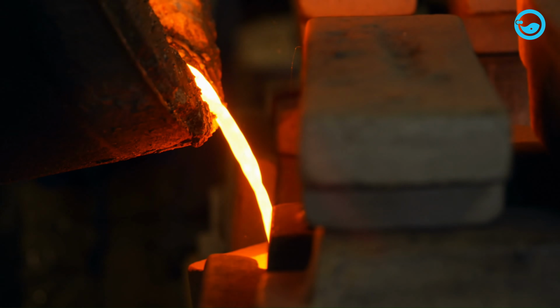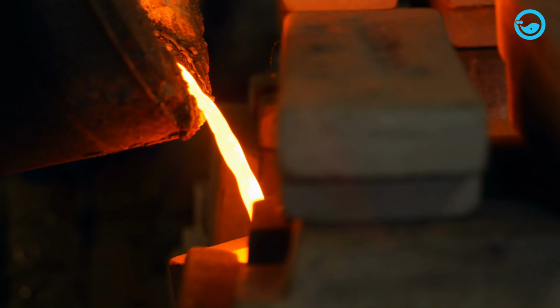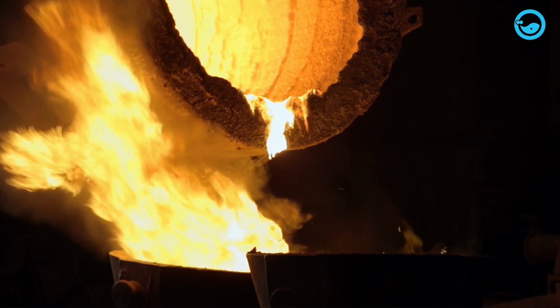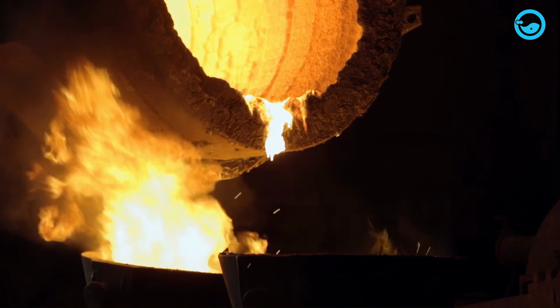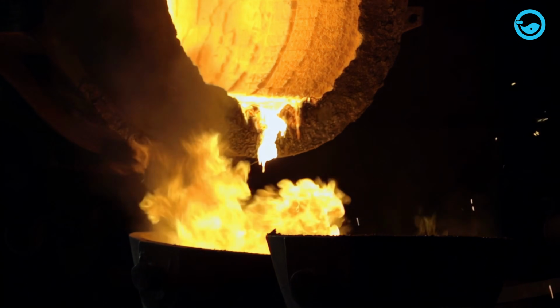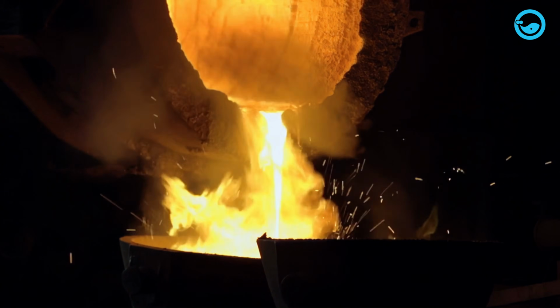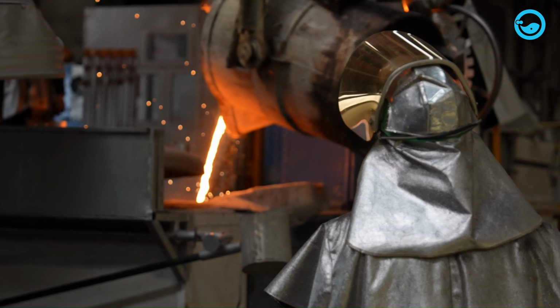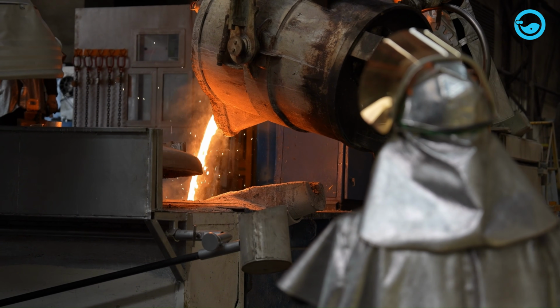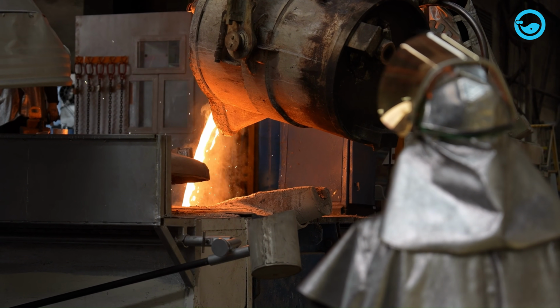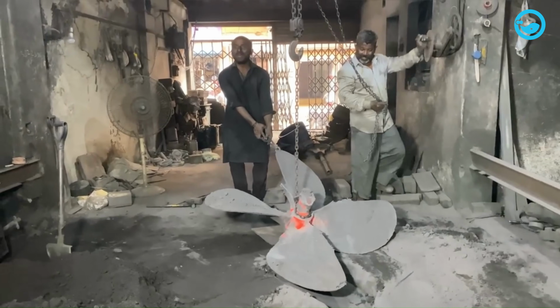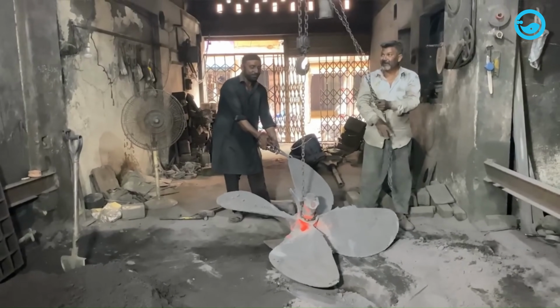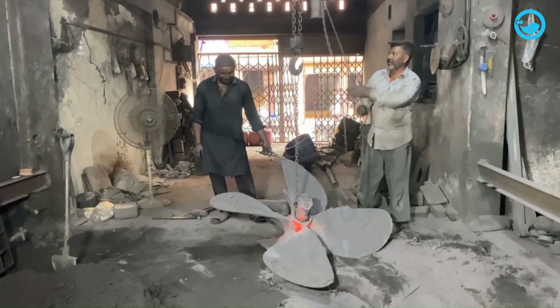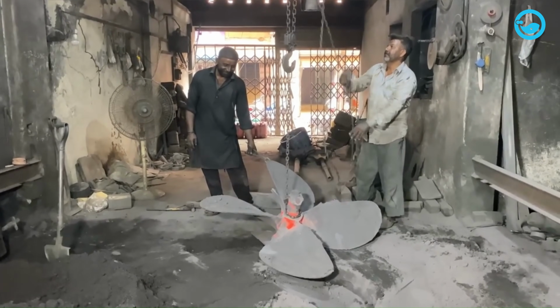Under the unified requirements used by major classification societies, the foundry must keep chemical analysis records, and at least one tensile test specimen is taken for each ladle. Test samples are cast in the same type of mold material and cooled under the same conditions as the propeller. Those samples cannot prove that every inch of a huge casting is perfect, but they do show whether the metal from that heat has the required mechanical properties.